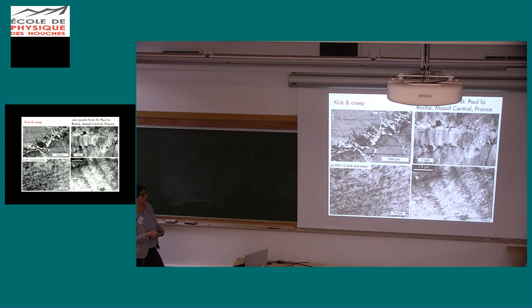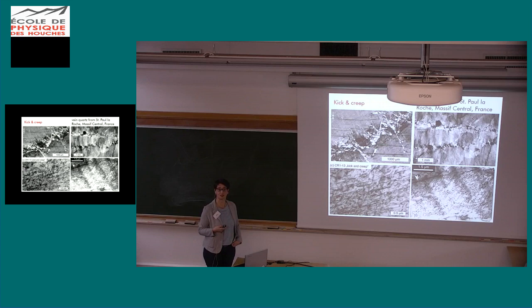We do see strongly localized deformation and recrystallization. So we have again these areas where we increased the stored strain energy during the kick event, and then these are areas of recovery and recrystallization during creep. And so we do see high dislocation density. We see dislocation walls in these areas where we see something similar to deformation lamellae, but it's again recovered low temperature plasticity basically. So it's low temperature plasticity, but additionally some recovery in this area.